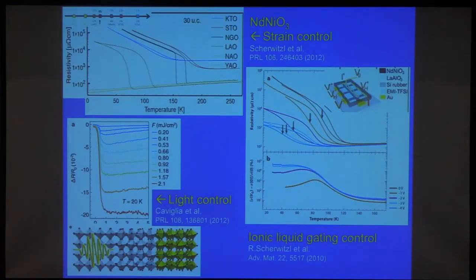And this is an example where this nickel oxide that I mentioned before is grown on a substrate and hit with a mid-infrared femtosecond laser pulse, which is resonant with one of the structural modes of the substrate, and that actually changes transiently the crystal structure of the material into a new structure which switches the material from a magnetic to a non-magnetic state. Okay, so this is really the frontier of the field, is not only trying to understand these materials, but actually trying to control them into doing things that we want them to do.